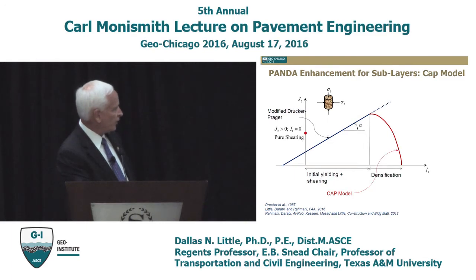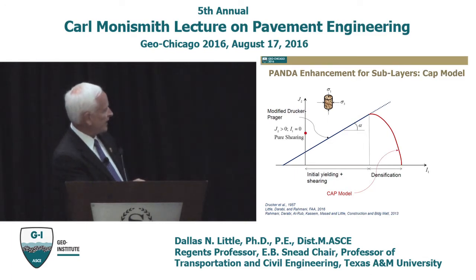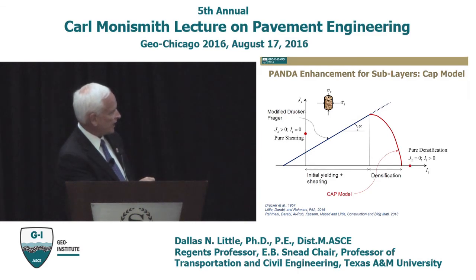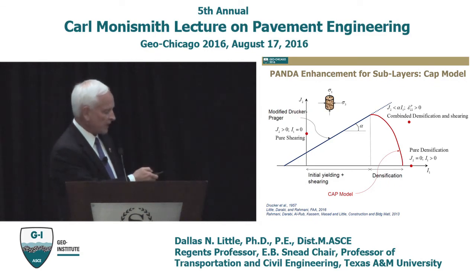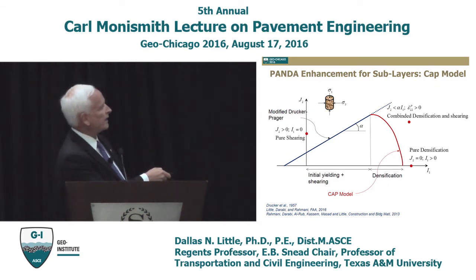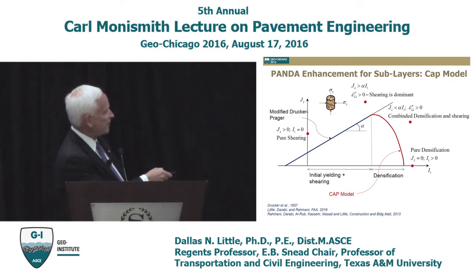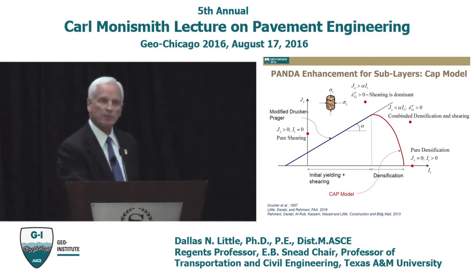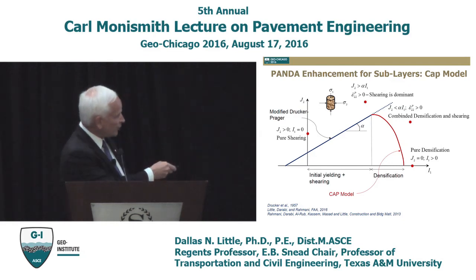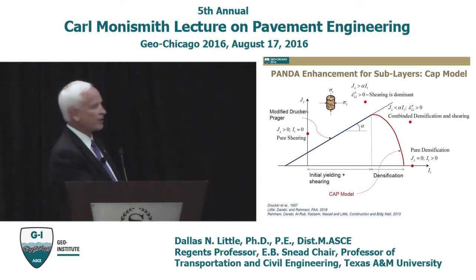And of course, if you look through this, you're going to find what happens if you have pure shear, what happens if you have pure densification, and where you have a combination of shear and densification. But the key point here is simply that using only a Drucker-Prager type model without the cap, you'll never know if you're getting plastic deformation unless you're above the yield surface. And you'll never know if you're above that densification surface unless you apply the cap model to it.